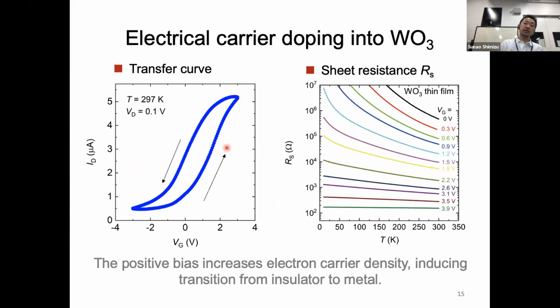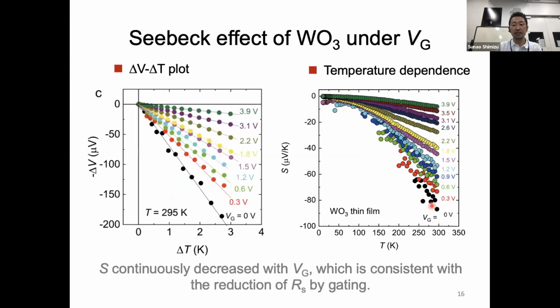The left figure shows the transfer curve. When we apply positive gate voltage, the drain source current increased. This means that the resistance decreased. The right figure shows the temperature dependence of resistance of the tungsten oxide thin film. When we apply zero gate voltage, this material is completely insulating. But when we apply positive gate voltage, the resistance decreased gradually, and finally it shows a flat metallic temperature dependence of resistance. At the same time, we also measured the Seebeck coefficient. Please look at the right figure. As you can see here, the Seebeck coefficient also changed gradually with changing gate voltage. This means that we can systematically control the carrier density and also the physical properties of the semiconductor by using the electrolyte gating technique.